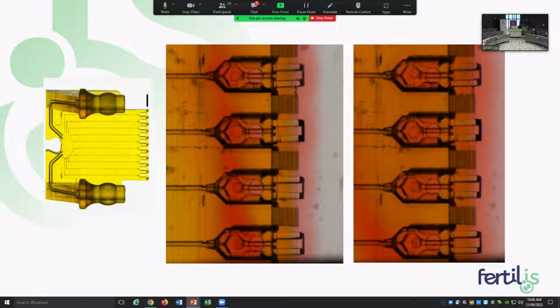As with the cradles, the nest was post-processed in sequential immersion of 3 consecutive isopropanol baths. In addition, though, we were flushing each of the channels with isopropanol with a pump up to 3 bar. This level of precision has only been made possible by the use of 2pp.